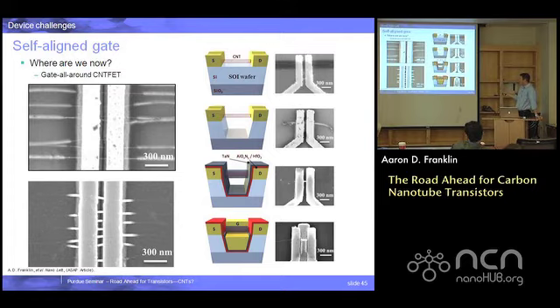Yeah? The self-alignment, I'm not going to get into in great depth. What we've done most recently is more exciting than what I have here, so I'll tell you what it is. And that is, we designed this structure so that what you do is backfill the whole thing with something like tungsten, where we would sputter it on and it would cover everywhere and fill these little trenches, and then polish down the tungsten in a CMP process. And we've now done this on our 200 millimeter wafer fab that we have at our facility in Yorktown Heights, and shown a selectivity between the tungsten and palladium where it gives a nice polished surface like this. This one is actually from a liftoff little trick that keeps the gate self-aligned to the contacts, but it has a much better manufacturable tie.